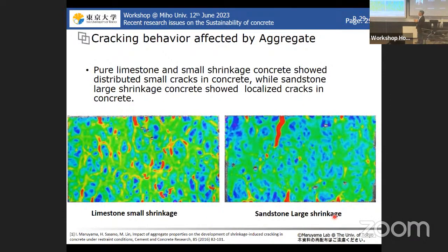I can explain something. In the case of the sandstone aggregates, it seems that the bond between the cement paste and the aggregate is very weak. In this case, once the cracks happen and lead to the aggregate, and the aggregate is shrinkable, and also the bond is weak, these cracks penetrate along the ITZ. And if it develops further, the stress here will be reduced due to the crack opening.